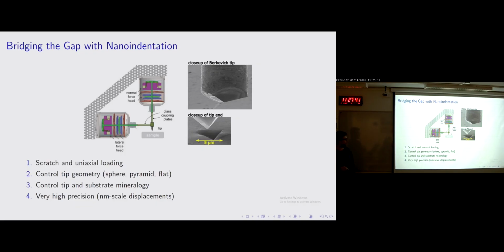We can control the tip geometry. You don't have to use this type of geometry, this three-sided pyramid. You can use a flat punch, a sphere, a four-sided pyramid. And we can also control the tip material and obviously the sample material itself. So we can test different chemical environments, chemical contacts.